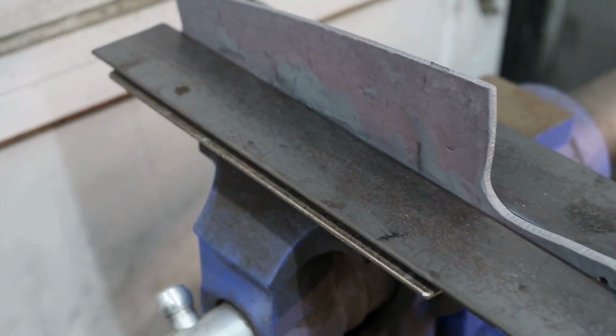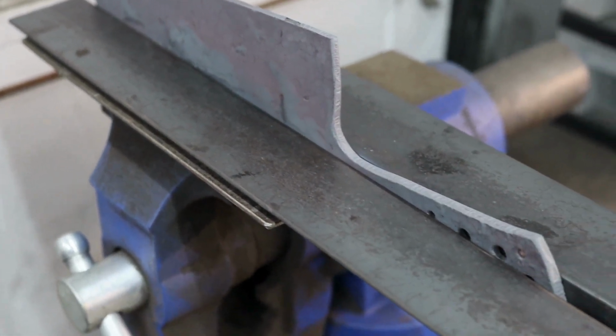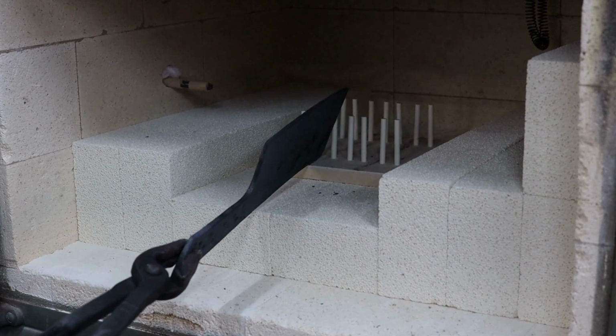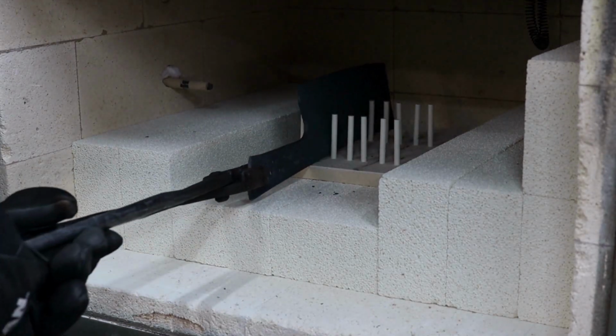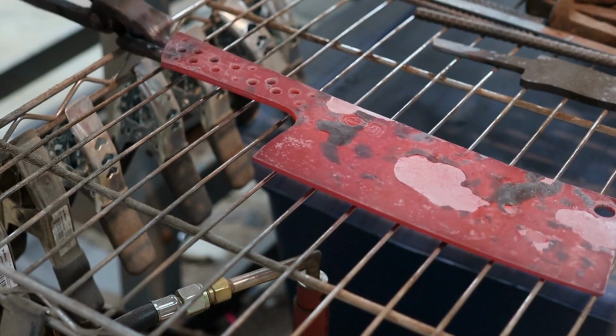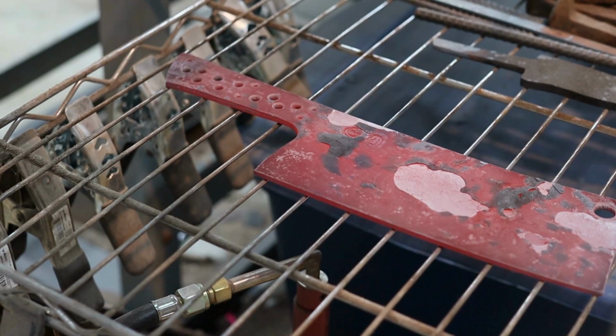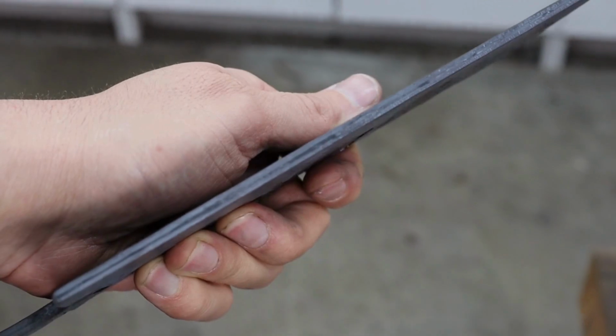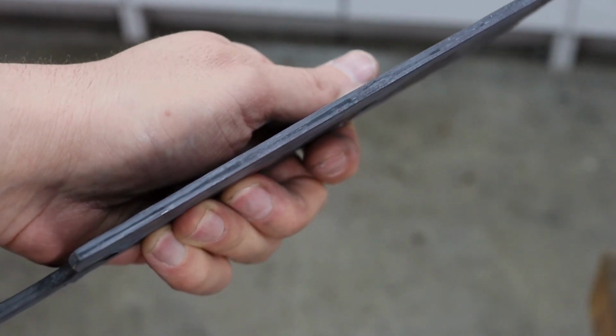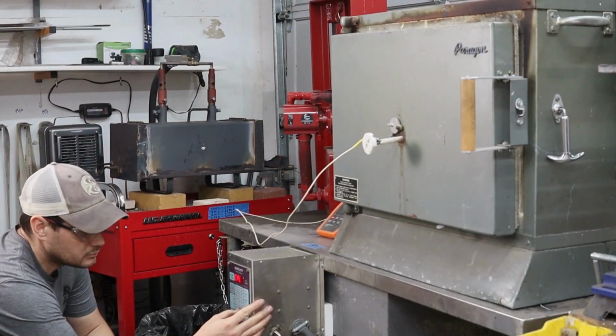I'm going to run 3 normalization cycles to dissolve the carbides and refine the grain structure of the steel. Those cycles will be at 1650, 1500, and 1400 degrees Fahrenheit. There's kind of a cool look at the darker color of the core steel centered along the edge.